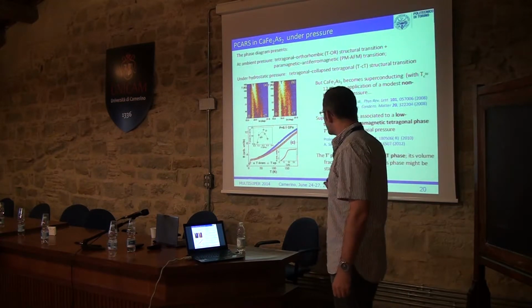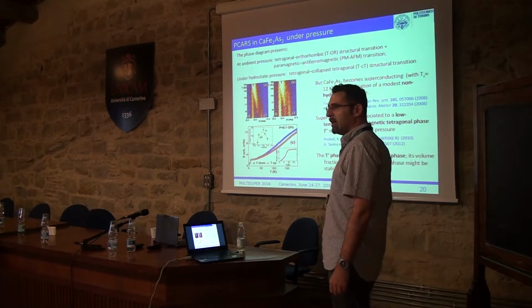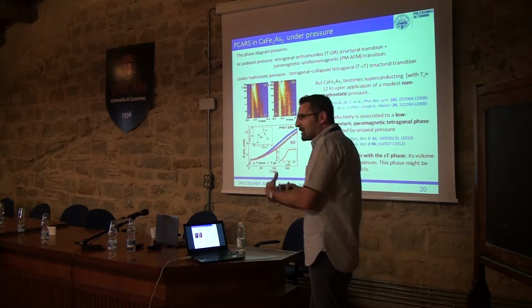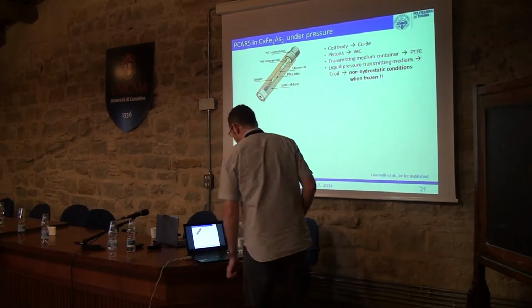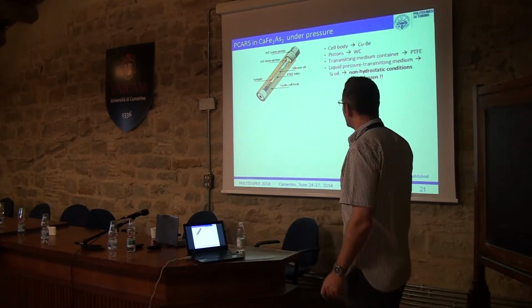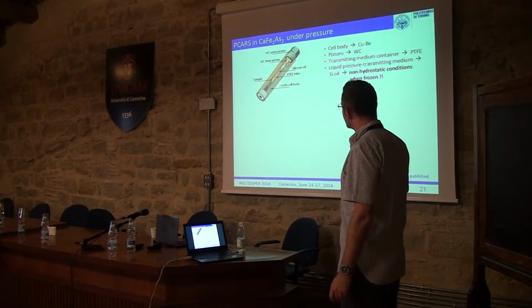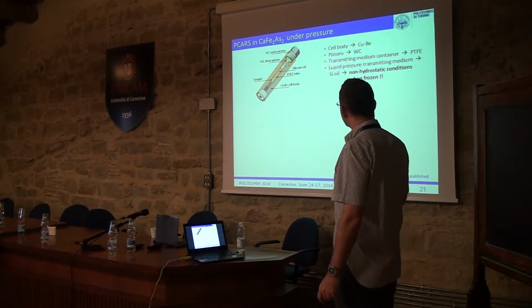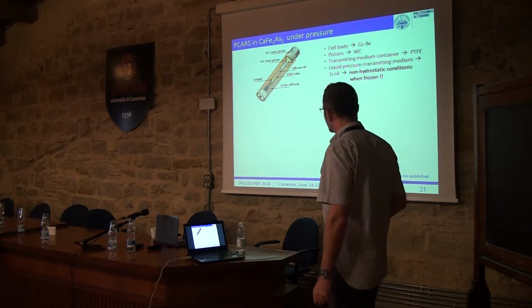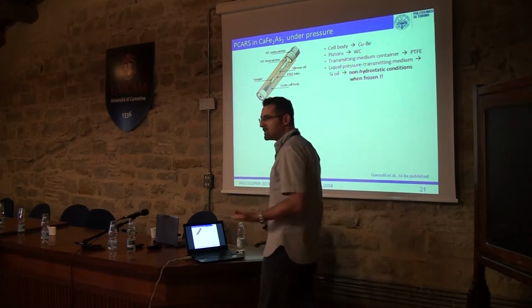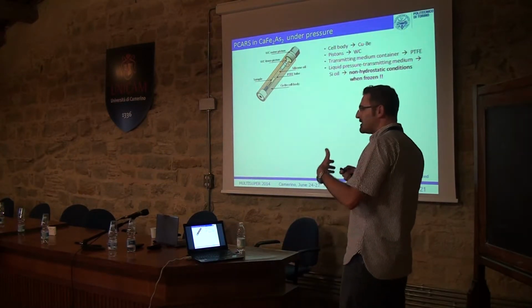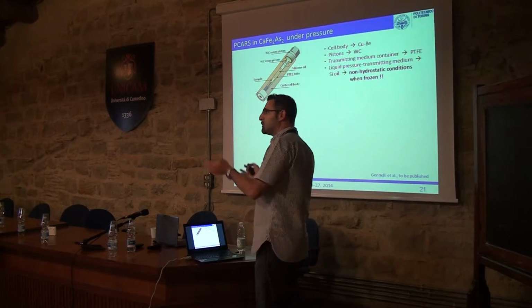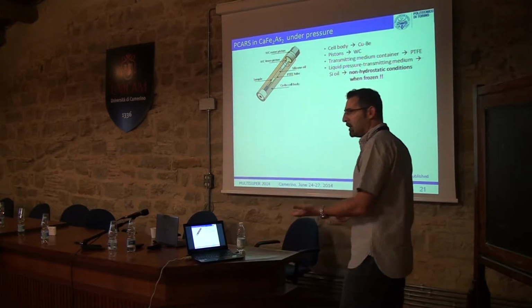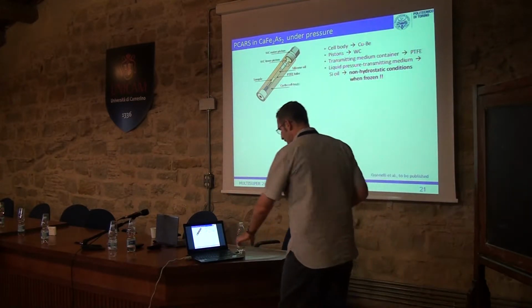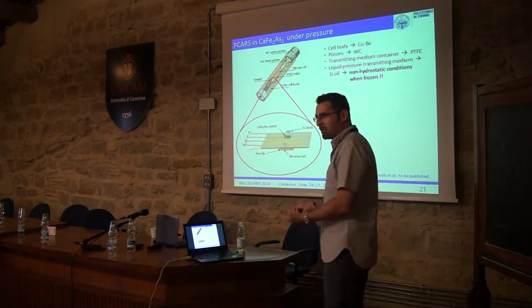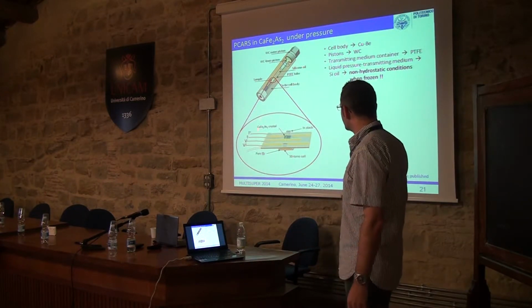So we are wondering, what happens here? What is the Fermi surface here? What happens to the gap here? What are the characteristics of the superconducting phase in this case? Then this is the mounting of the sample. The sample is in a pressure cell. The pressure transmitting medium is silicone oil, which applies a hydrostatic pressure at room temperature, but when it freezes, it applies a pressure which is no longer hydrostatic. And this is what we need because we want to observe superconductivity, of course. This is a sketch of the mounting inside.